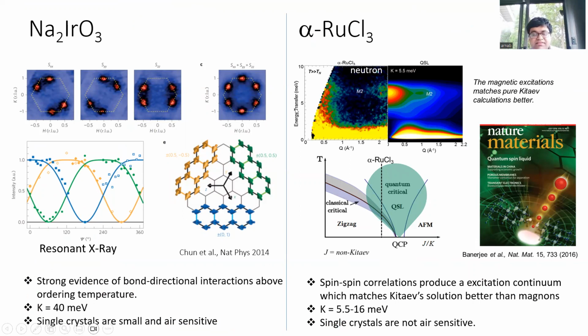So there were some beautiful experiments done in sodium iridate where they showed these bond-dependent interactions in resonant X-ray scattering. And then there was our paper where we showed that in alpha ruthenium chloride, you get these signatures of these Majorana fermions with neutron scattering.